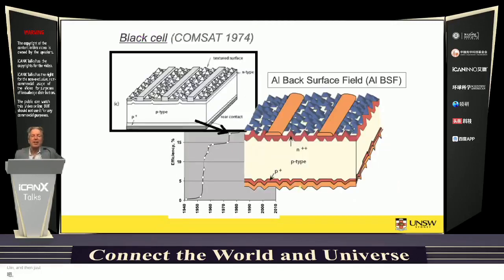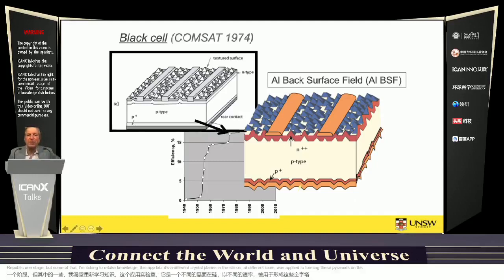And then just a couple of years later, other researchers at ComSat Lab went one step further and applied, again, some of the technology that had been used in microelectronics for selective etching. So there were things called V-groove transistors that were popular at one stage, but some of that etching technology that etches different crystal planes in the silicon at different rates was applied to forming these pyramids on the surface of the solar cell. So the pyramids are defined by intersecting crystallographic planes. They have pretty much the same geometry as the pyramids at Giza, but are a lot smaller. So just covering the whole surface of the device.